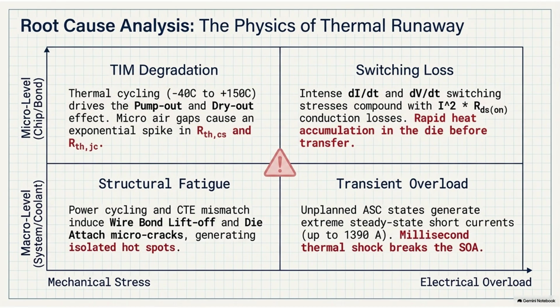Electrical resistance goes up, generating more heat. Thermal resistance goes up, trapping that heat. This creates highly localized, deadly hotspots on the silicon. It eventually pushes the silicon past its intrinsic temperature limit, causing complete thermal runaway, melting the die, and triggering an explosive short circuit. Okay, so everything we just discussed, the TIM pump out, the wire bond shearing, that is what happens over thousands of miles. That is the slow, long-term degradation of the hardware.